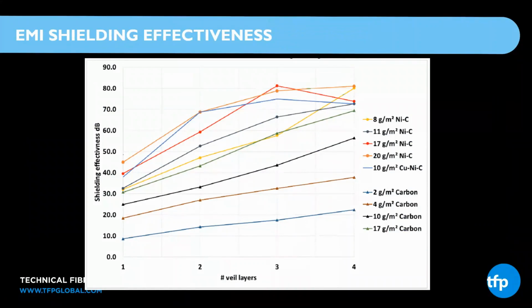This was in the same experiment as the previous slide. There were glass and epoxy prepregs, but here we attempted to stack our veils to see if that would add to the EMI shielding effectiveness. This is a little bit busy, but let's look at just the 17 gram per square meter nickel coated carbon. With one layer, it yielded 40 decibels of shielding effectiveness. If you had two layers of the 17 GSM, or another way of saying that would be 34 grams per square meter in total, you got 60 dB. You can follow that graph up and you get 80 dB at 3 layers. For some reason, it dropped at 4 layers.